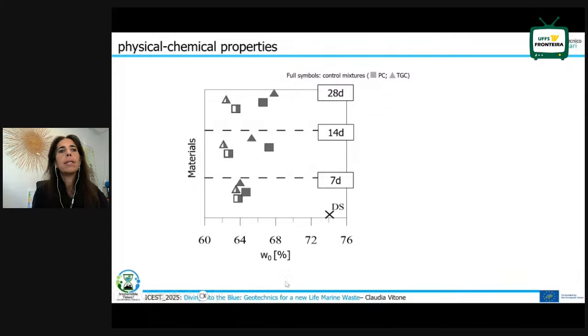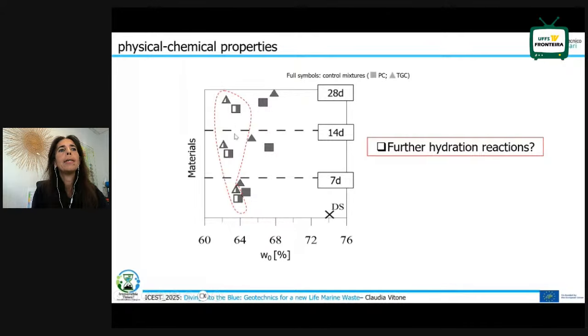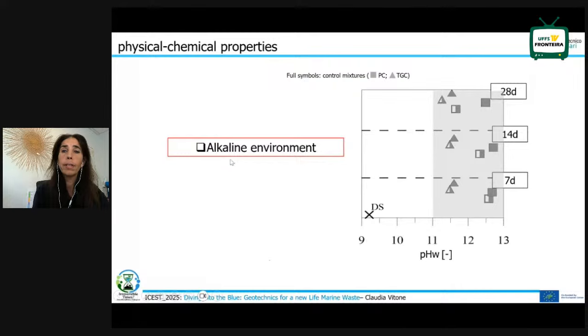Other results. This, for example, is the water content through curing time, where we have compared the water content of the mixtures with shells with that of control mixtures. As you can see here, the water content of the mixtures including the shell powder is lower than that of the control mixtures. So this is probably indicating that further hydration reactions are occurring. So this shell powder, although obtained at a very low temperature, so without calcinating the shells, is also having an active role in these mixtures.